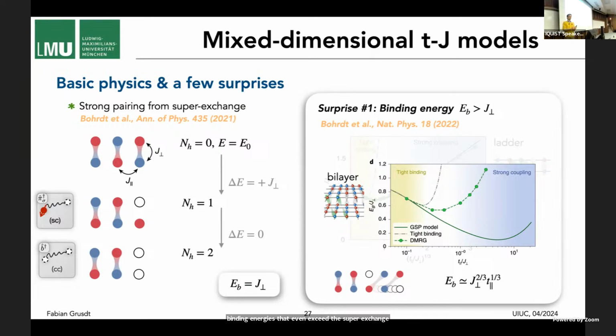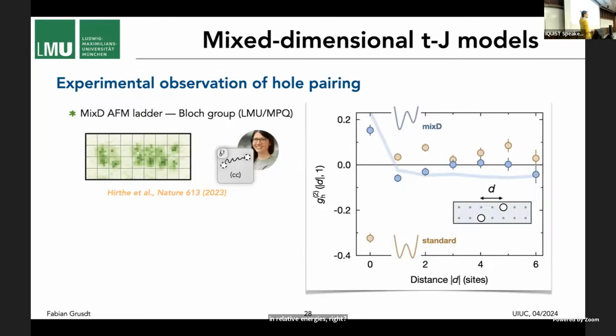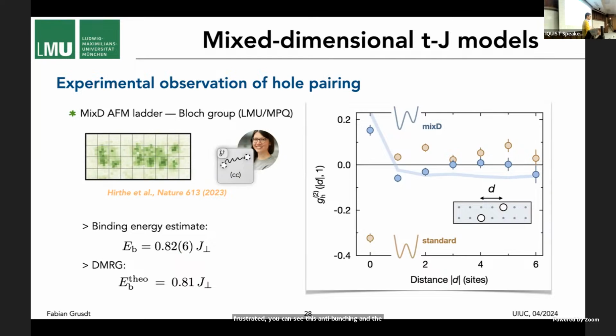Okay, now for the cold atoms, I told you they're so hot in relative energies, right? So this is obviously a good system to look for pairing, and that's exactly what they did. So they realized this mixed D system in a ladder, and then they measured the G2 correlations between the holes again. And you can see that if they use this mixed D setup, on the blue data points, there's clear bunching of holes next to each other, and that means there's binding of holes. Whereas if they use the standard 2D ladder, that's more frustrated, you can see there's anti-bunching and the holes would not bind at these energies. We estimate binding energies, they agree with numerics, so that's great.